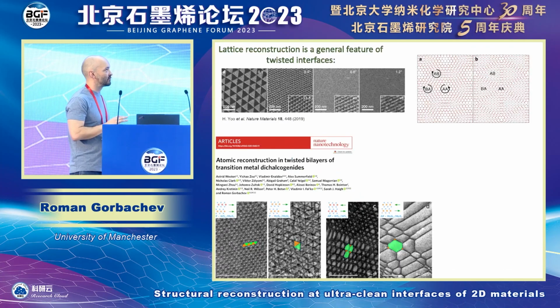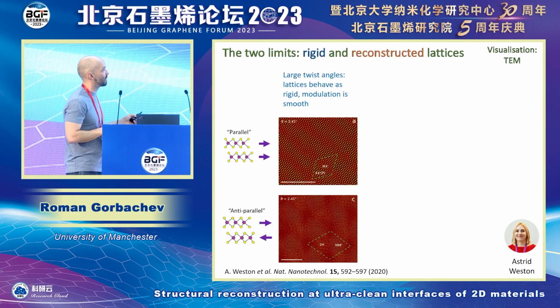If you start using these techniques, there is also, of course, TEM, so you can look at atomic resolution, and you start visualizing these domains. In graphene, it's actually very simple. You have triangular domains of different stacking. The period changes with the twist angle, so everything is straightforward. In TMDs, it's a lot more complex, because now you have no inversion symmetry, and you have two possible orientations. These are the so-called parallel orientation, where the unit cells are parallel, and anti-parallel, when you basically rotate one layer 180 degrees relative to the other.